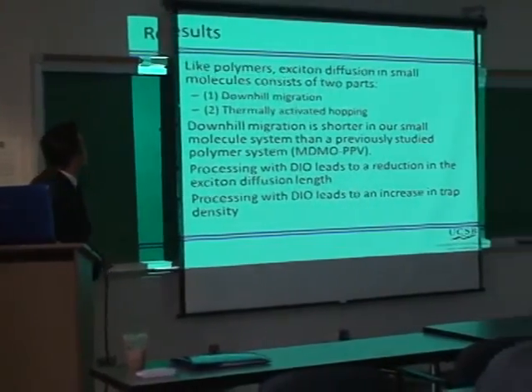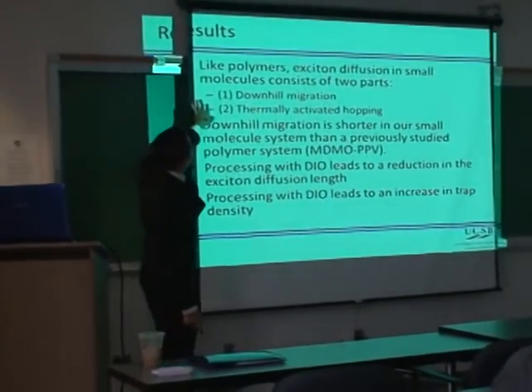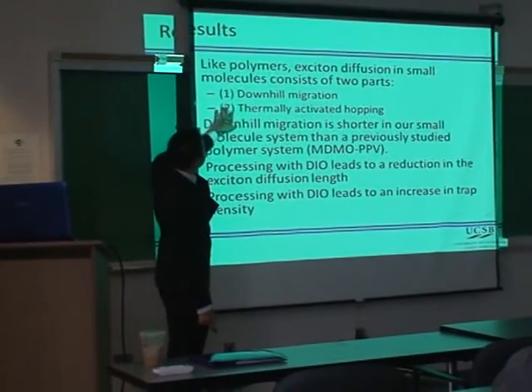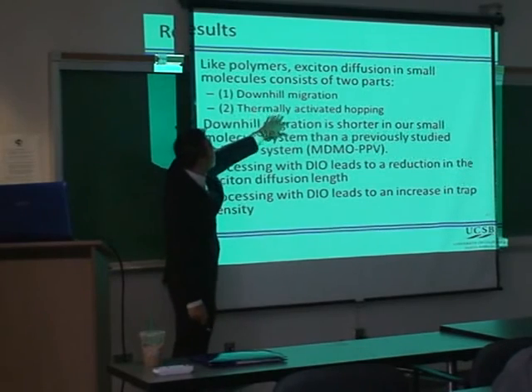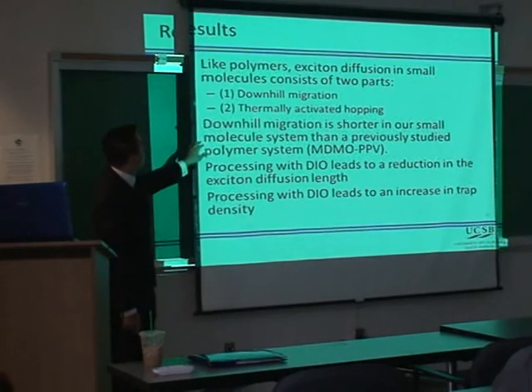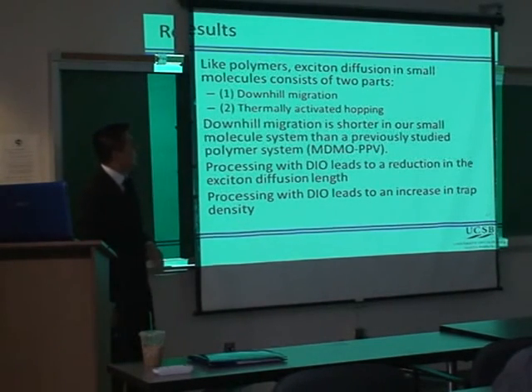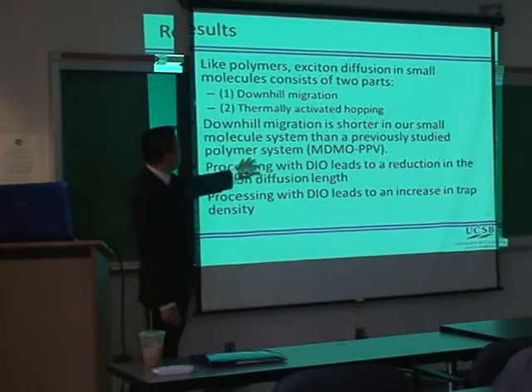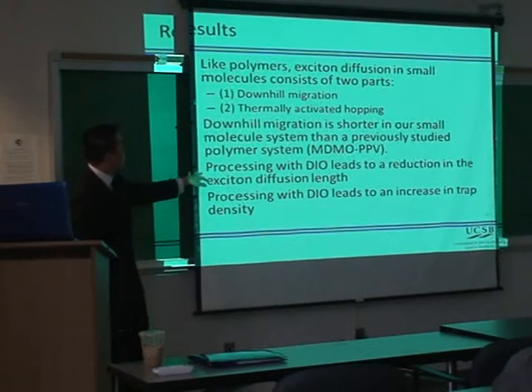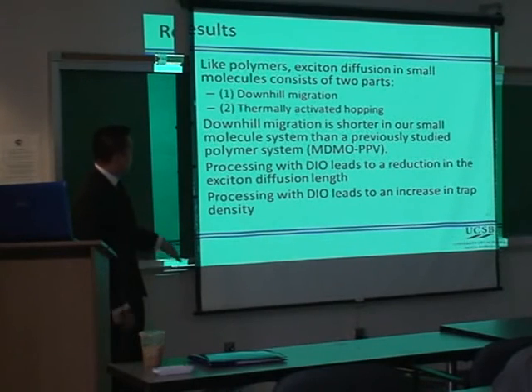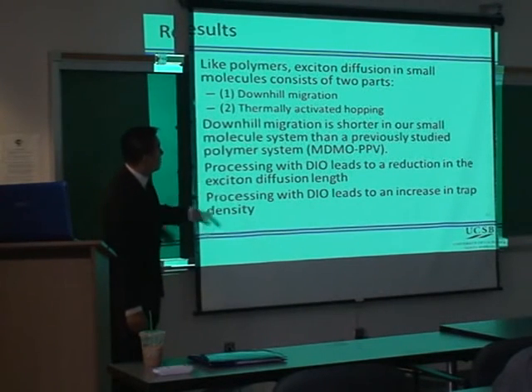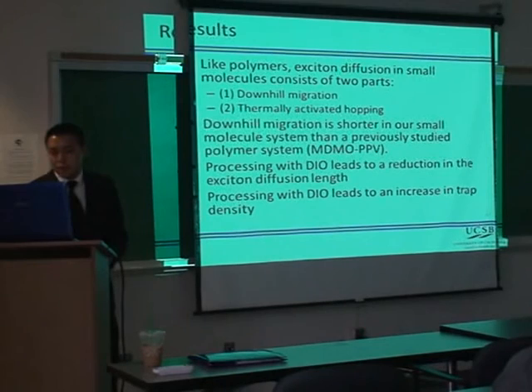So just to quickly summarize, like polymers, there are two phases of exciton diffusion: the downhill migration and the thermally activated hopping. That's what we confirmed. And we found that downhill migration has a smaller contribution in small molecules compared to a polymer system. We also find that processing with DIO leads to a reduction in exciton diffusion length and an increase in the trap density. And yeah, that's pretty much the vision.